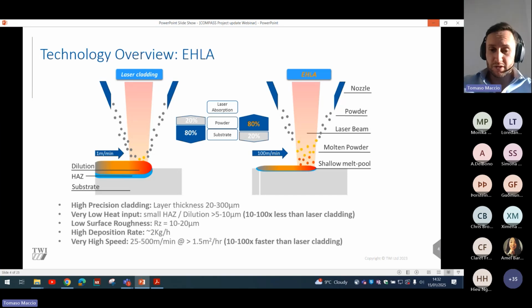We get very low heat input as an advantage. Low surface roughness, which is definitely a benefit for crevice corrosion, and a high deposition rate and high speed, so we can go up to 500 meters a minute with the EHLA technology. This is just a small video of the melting process in flight. You can see the nozzle above, powder's being fed into a central position, and the laser beam is hitting it. In this case, it's not fully melting it, it's just sintering the powder and then depositing it onto the substrate. But it's a very good video just to show in flight what is happening for the definition of EHLA.